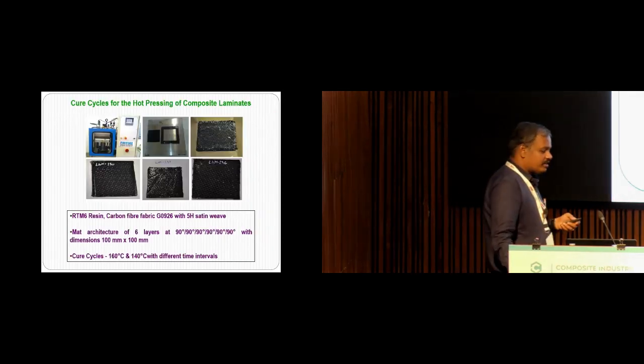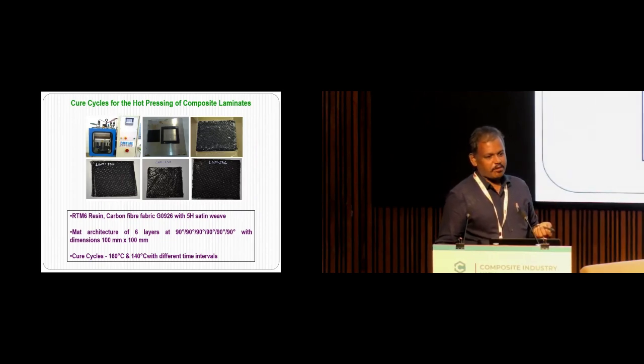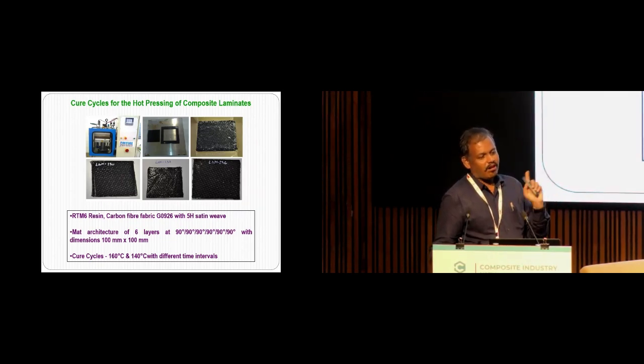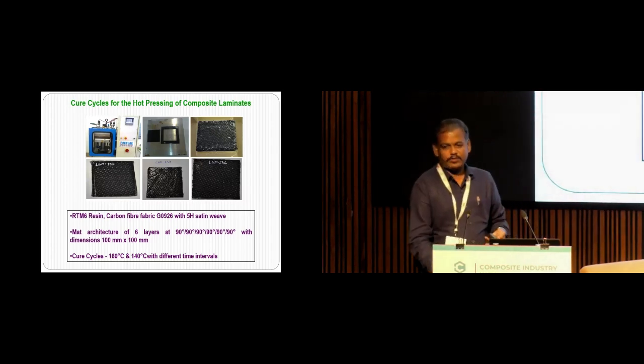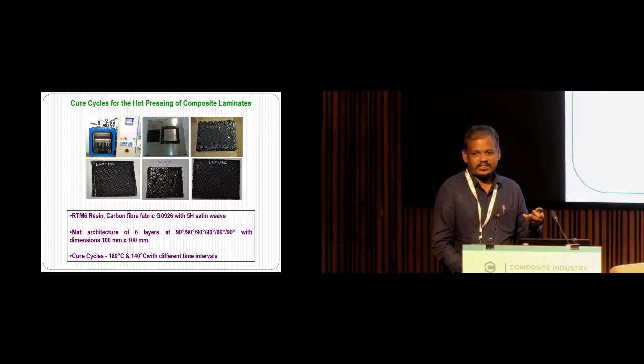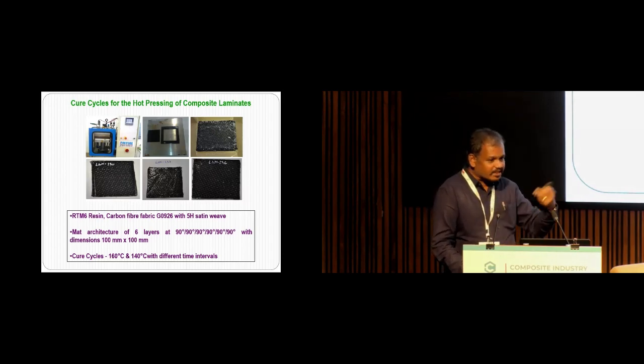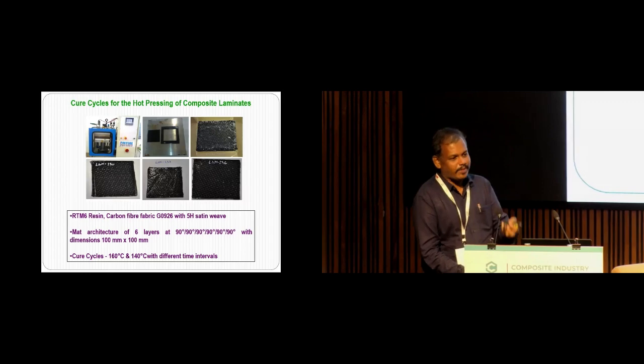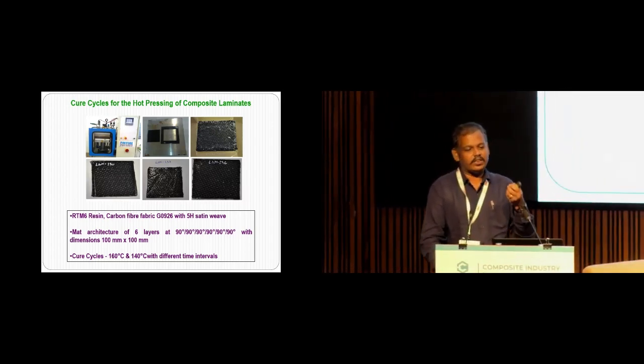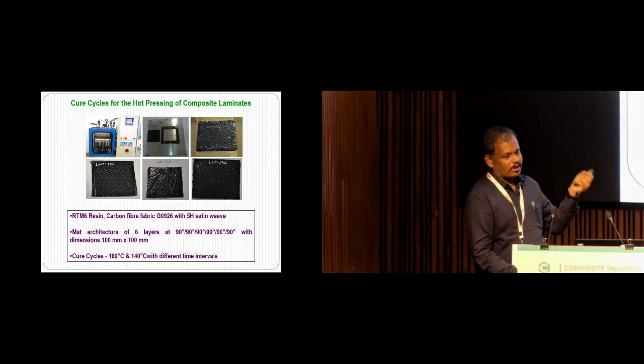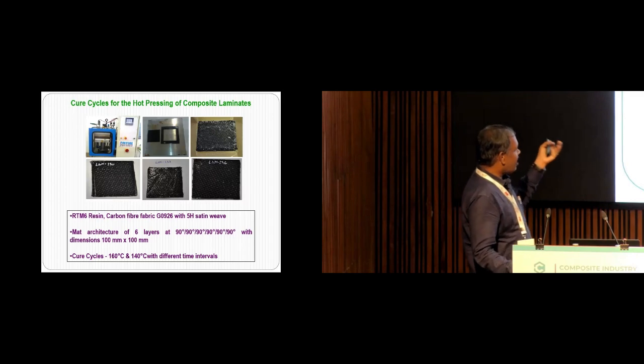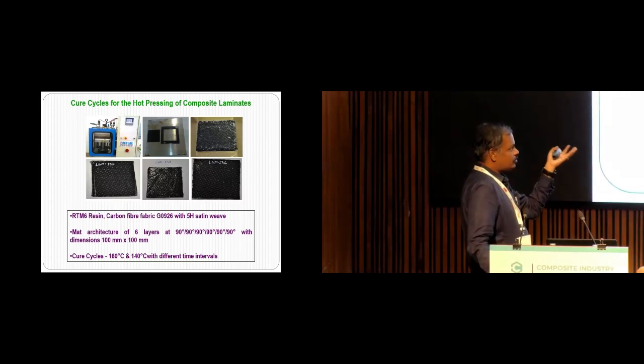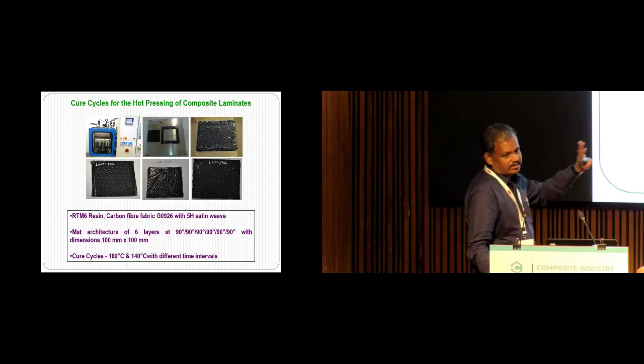Now, we have performed DSC for the resin, but what we are interested in is the semi-cure of the composite panel. Since the composite consists of carbon fiber and RTM6 resin, we may expect that the carbon fiber offers some resistance to heat transfer and degree of cure. So we have to compare the cure evolution behavior of the composite panel with that of the resin. We performed this with a hot press process. Here we used RTM6 resin and carbon fiber fabric G0926 with a 5H satin weave architecture, with 6 layers at 90 degrees. These parameters were taken from Airbus.